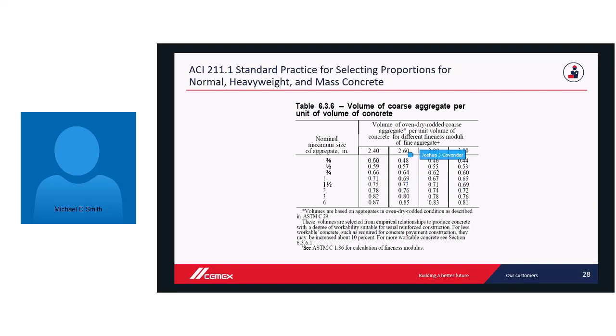So let's say if we're at 1 inch, and it was a 2.6 fineness modulus, you multiply 0.69 by the amount of volume that you're designing for. In this case, a cubic yard of concrete is 27 cubic feet. Again, this gets pretty deep into the calculations, in the weeds, but ultimately it would give you an amount of aggregate. You do the formula, and you come up with, say, like 1,400 pounds of rock.